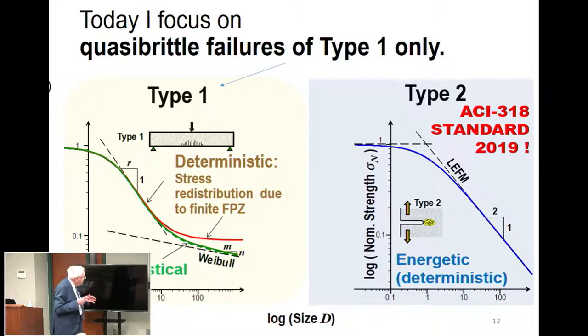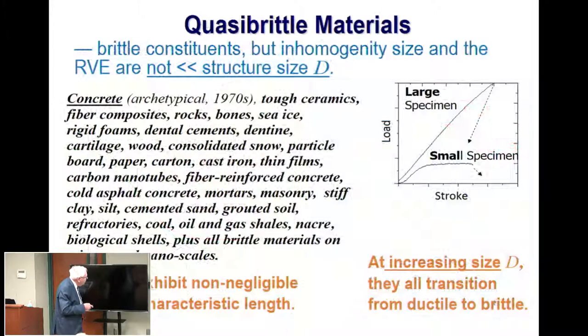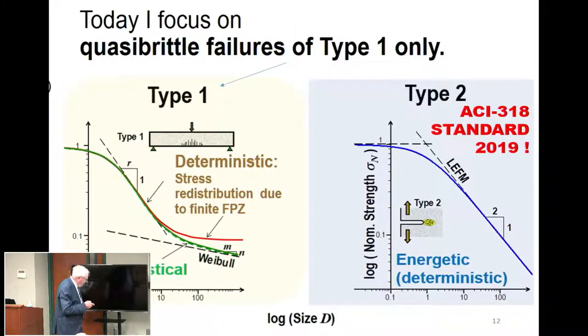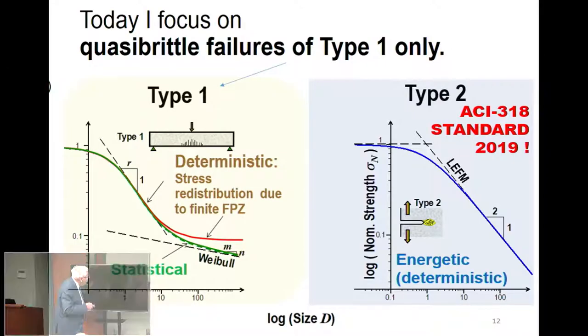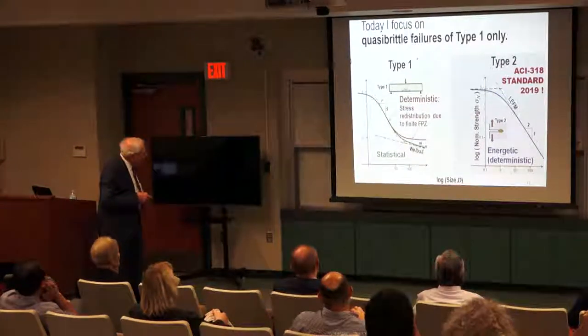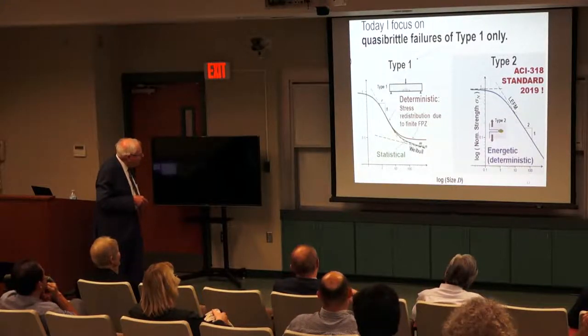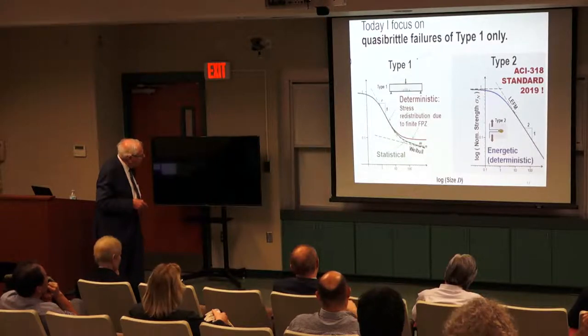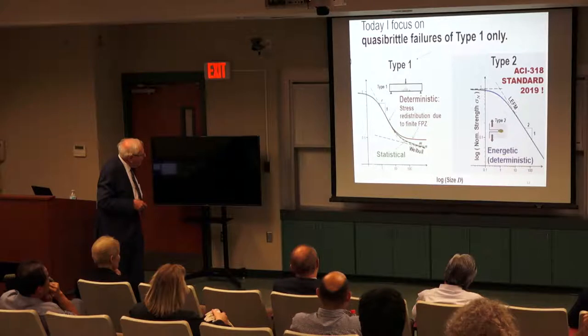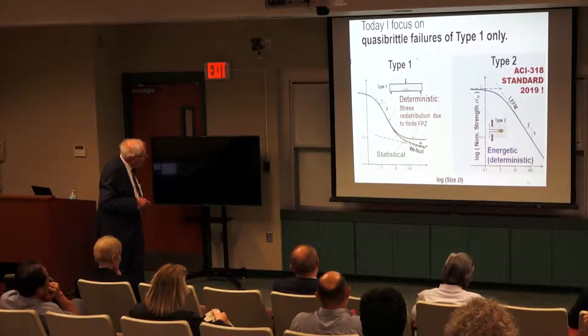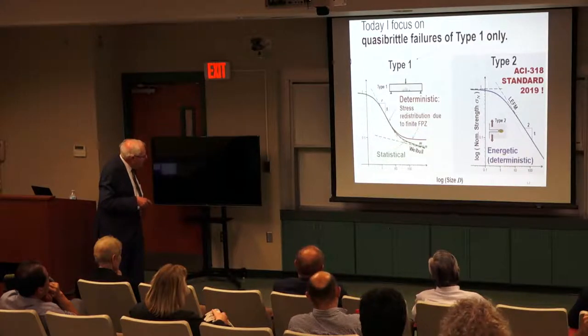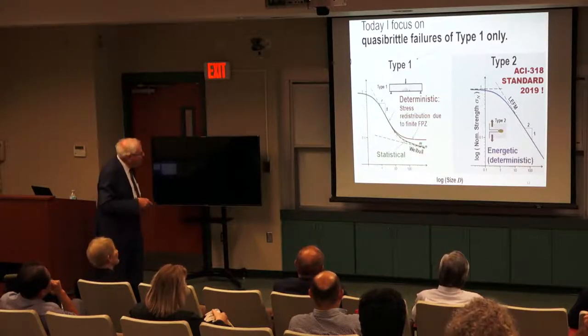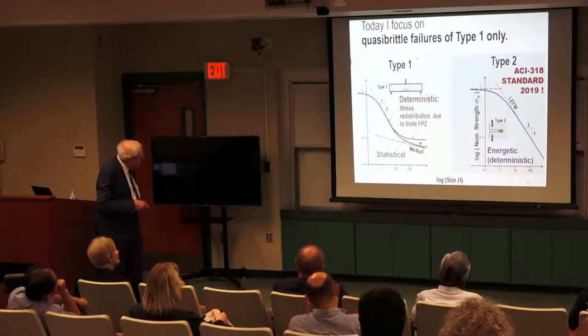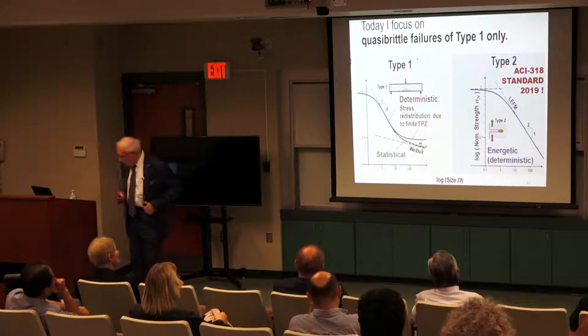The specimen becomes unstable as soon as you form a full fracture process zone and the macro crack starts to propagate. So this is still the damage zone or fracture process zone, and the crack starts going from here, and that's the moment of failure. So it can be considered deterministically. If you add statistics, you find out eventually it goes to Weibull statistics exactly. This is a plot in log-log space. The power law is a straight line: logarithm of load, logarithm of size, and Weibull statistics is a power law, so it's a line of constant slope. I will discuss only this kind of failure. And statistics is extremely important for these very small sizes, and very often we have to consider this.